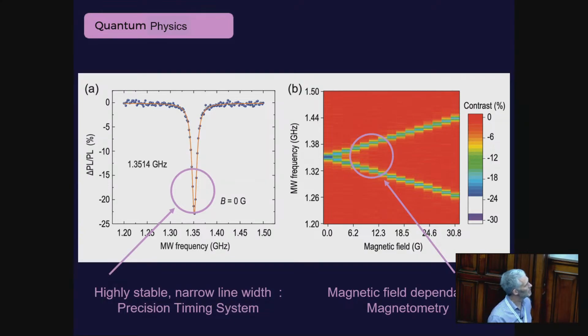On the other side, we've got magnetic field dependence. We've got a magnetometer. The clever thing about magnetometers on this is because silicon carbide is a hexagonal close-packed lattice, that direction and that direction are not the same. And so actually with one pair of defects, I can look at that direction and that direction at the same time. I've got a perfectly orthogonal magnetometer with one sub-micron feature size. All on the same system.